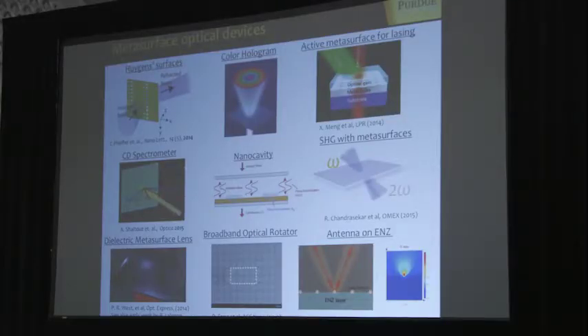Arguably one of the most important devices in optics, used most broadly, is the CD spectrometer. When it comes down to biomedical applications, that's what they do all the time. They need to distinguish between different molecules with different chirality. And for that, they measure the difference in absorption between left and right circularly polarized light. It's a complicated experiment, time-consuming, bulky. So by using the photonic spin Hall effect, we designed a single array, 100 nanometer thick, CD spectrometer. If you send white light on this, the left circularly polarized light goes to the left, right circularly polarized light goes to the right, and different wavelengths go in different directions. It's that simple, and it's a very important device.